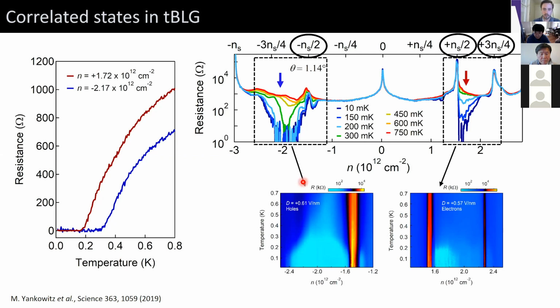So within a single material, we can make a phase diagram of the system by measuring the resistance as a function of charge carrier doping, which we can do electrostatically with gate voltages. And so at some densities, we see metallic behavior, the dark blue. At others, we see pockets of superconductivity, the cyan. And at others, we see correlated insulating states, the red and yellow. And we can freely tune between these just by changing the voltage knob.